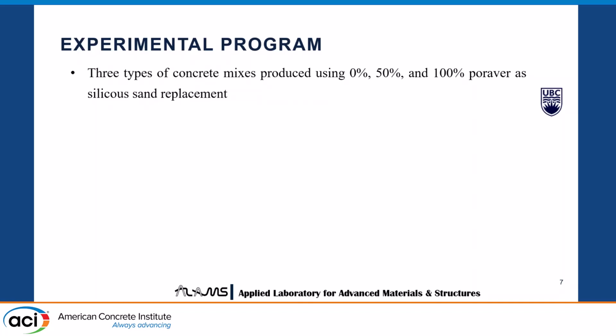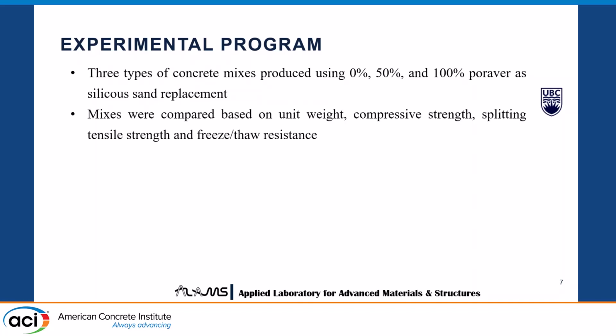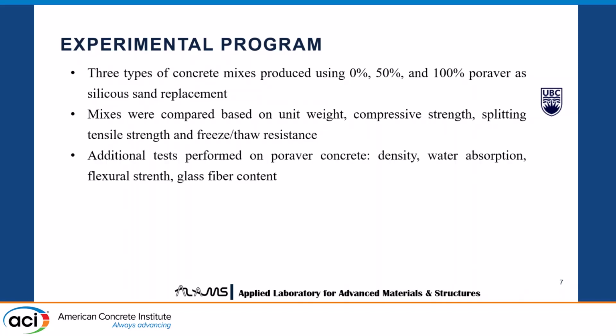So this is our three types of mixes, and we compared the mixes based on the unit weight, which is our main focus, then compressive strength, and we did splitting tensile strength, and we also did the durability test in terms of freeze-thaw resistance. And we also did some additional tests on poraver concrete, like the density, water absorption, flexural strength, and glass fiber content in the concrete. So this is basically an ongoing project. We are still doing some more tests.